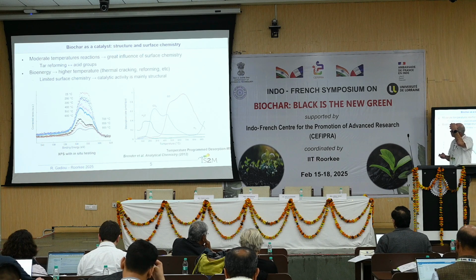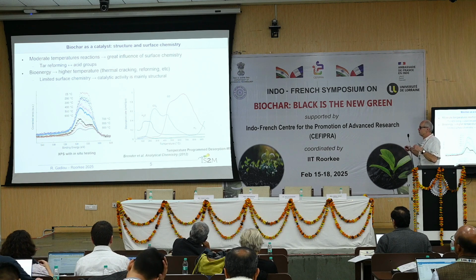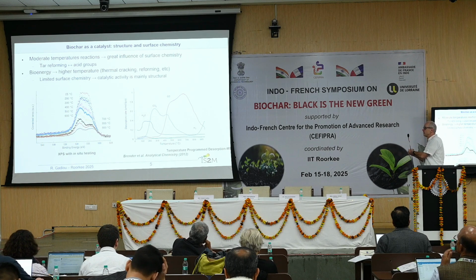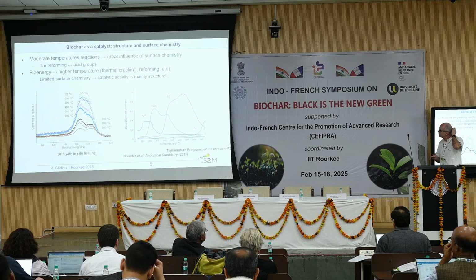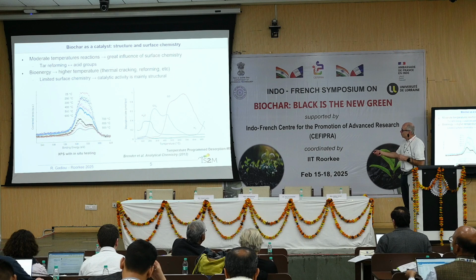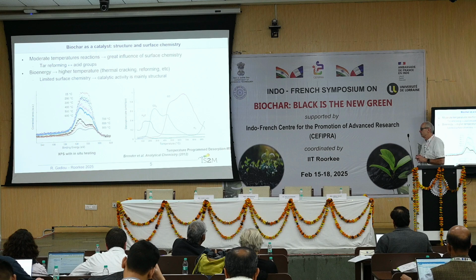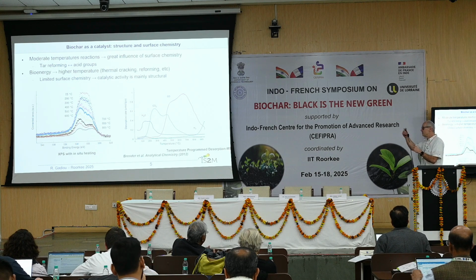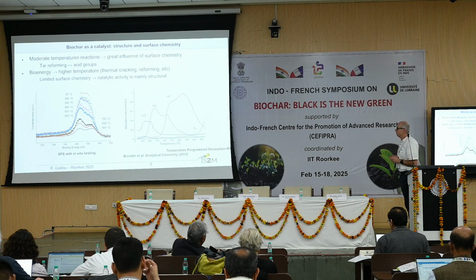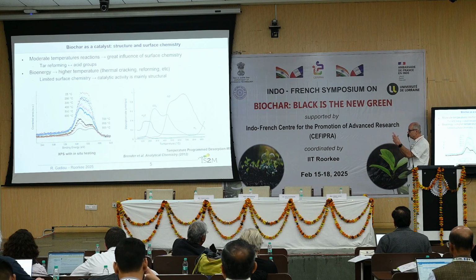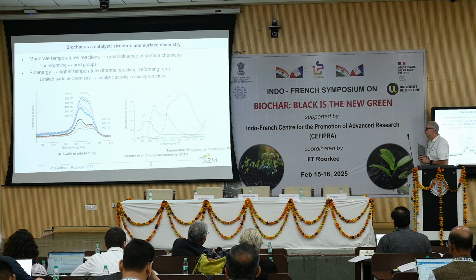First thing, when we look at surface chemistry, it may be of importance in catalytic application, depending on the temperature. Here you have an example of XPS analysis on the O1s peak. It's quantitative XPS analysis. It was done with in-situ heating in our XPS, and analysis in exactly the same condition. And then we can compare the intensity.